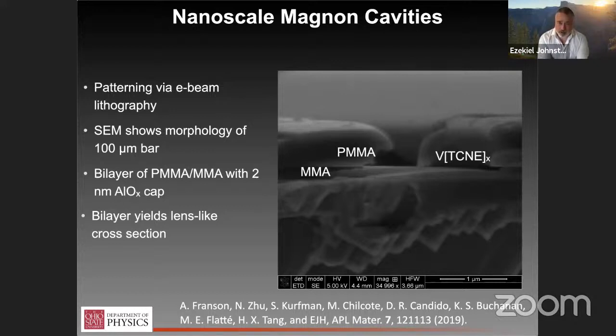Yeah, so we're definitely pursuing that. I think the challenge is, you can go to low field to reduce the FMR frequency to an extent, but it's still a pretty challenging regime for acoustic modulation. Hundreds of megahertz to gigahertz is tough for most oscillators. There are MEMS structures that can do that, but then we're limited by mass loading from putting a thick layer of V[TCNE]x on top. Those are not necessarily fundamental challenges, but they're significant technical challenges. We have some ideas that we think might work, but we're still pushing through that.